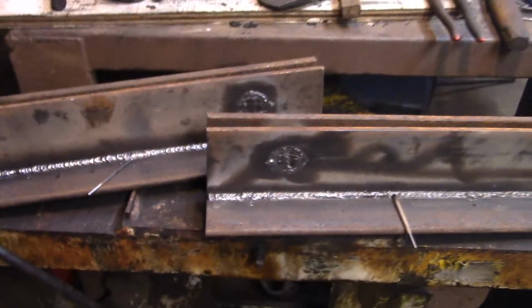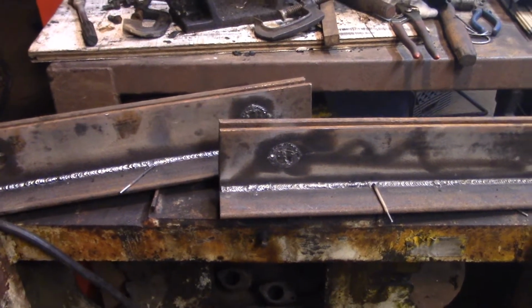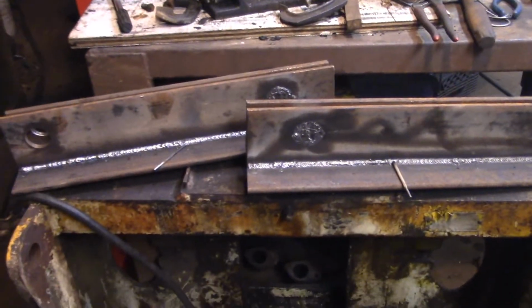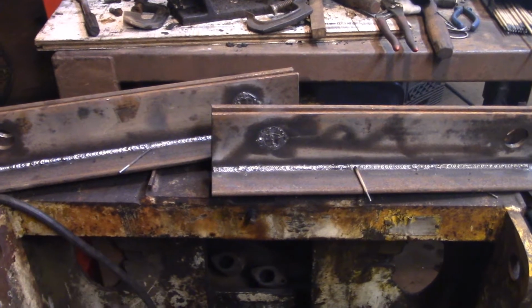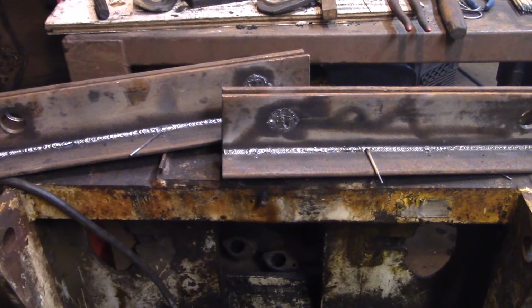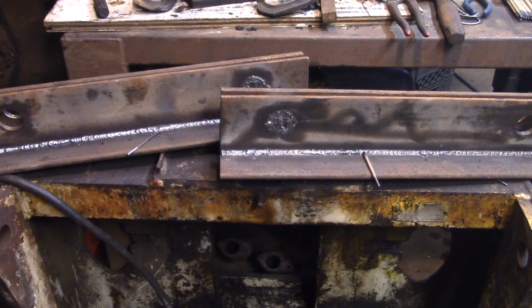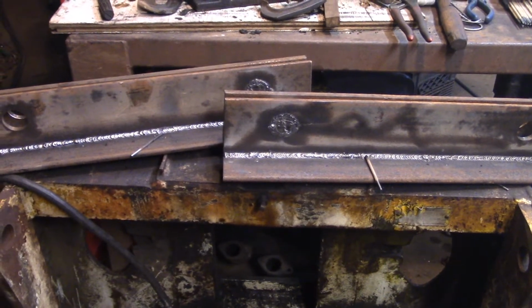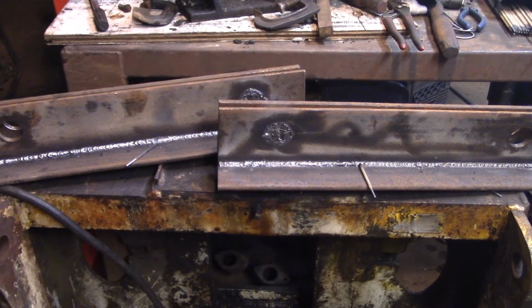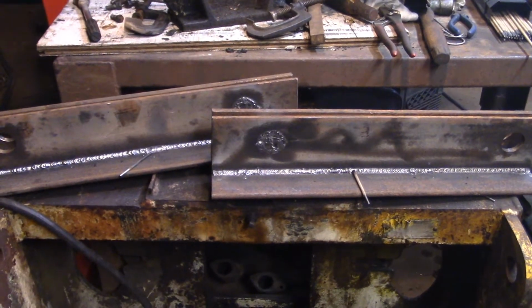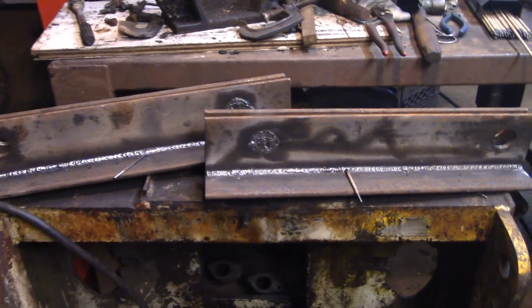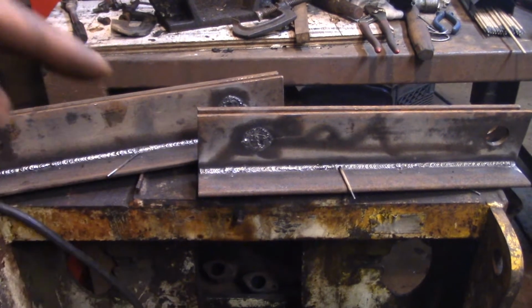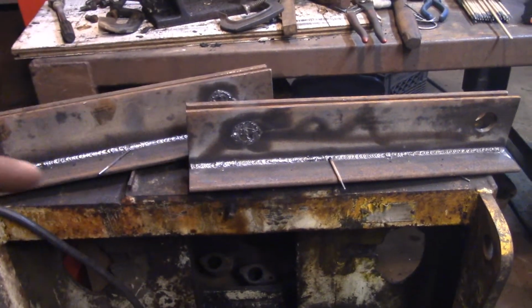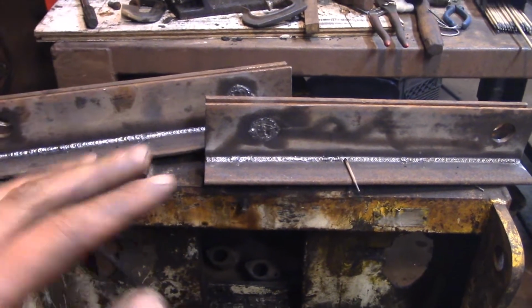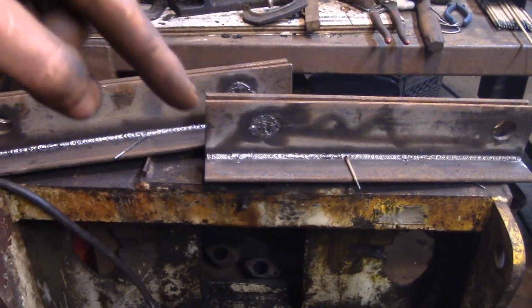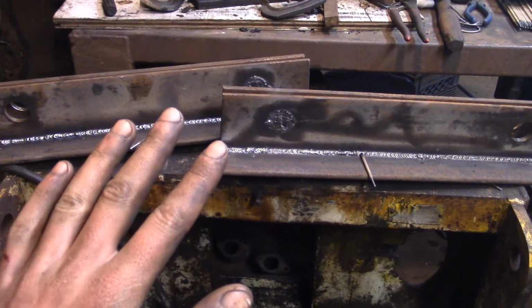And as Jody from Welding Tips and Tricks says in a couple of his stick welding videos, and I've taken this suggestion to heart, and I'll tell you guys as well, you should weld with a stick rod at the lowest amperage where you don't stick the rod. So basically, if you're starting out with a new rod or a new whatever that you're not familiar with, or maybe a welder where you're not familiar with the settings, start with a low setting and then keep increasing the amperage until you get to a setting where you're not constantly trying to start an arc and getting it stuck and breaking the stick off and trying to start an arc again and getting it stuck. Once you can strike an arc and just hold a nice arc, that's the temperature you want.